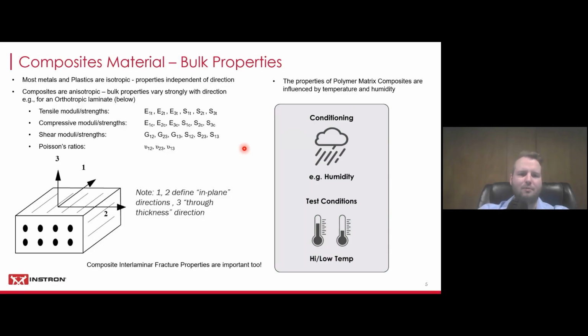Composites, on the other hand, are considered anisotropic, which means that their bulk properties vary strongly with the direction in which you apply a load. If we take this example down here, the black dots are supposed to be the fibers, and the lines show you in what orientation they are oriented. So we're talking about continuous fibers, and they are all oriented in this example in direction number 1, which will also be the direction in which the material has the highest strength if we were to apply a tensile or compression load in that direction. And then in direction number 2, it would be dramatically weaker if all of the fibers are aligned in this way. Direction number 2 will be very weak, and it will basically only be the strength of the matrix material and how well that is bonded to the fibers and how much strength that can carry, but the fibers themselves cannot take any of that load.